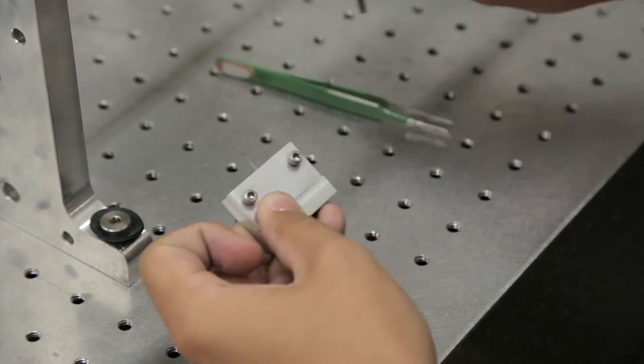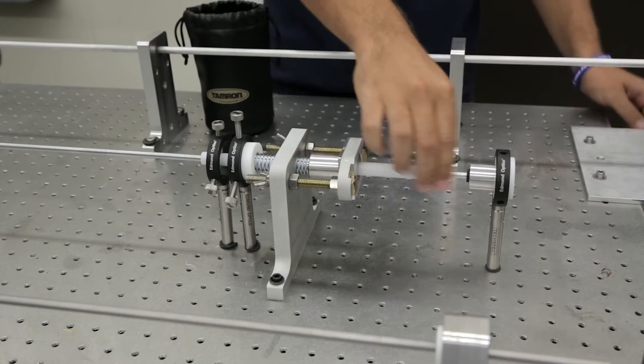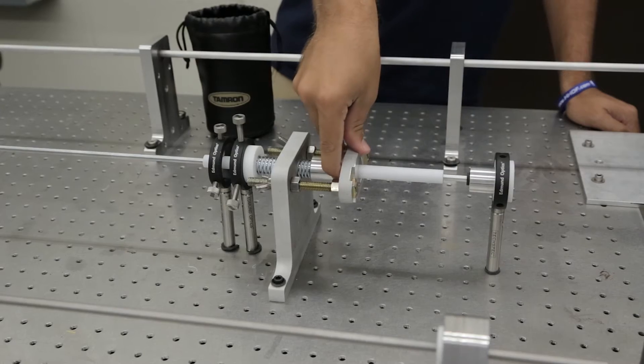What I do is I test the material at a variety of strain rates, because the polymer's properties change with the strain rate. I do uni-axial tensile tests on them at different loading rates, and plot the stress-strain curves and compare them.